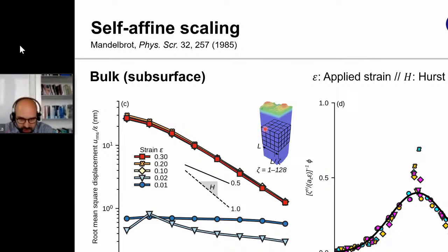So we again do this in these little boxes, and we change the size of these boxes. So here the x-axis is the size of the box. And of course, all the atoms move in slightly different directions. So we can again ask the question, what is the width of the distribution function that governs the movement of the atoms? And we see something very similar to the surface. We can collapse that onto a single universal curve. So what we see at the surface here is nothing else than a signature of the non-affine or non-laminar deformation profile of the subsurface deformation in these systems.